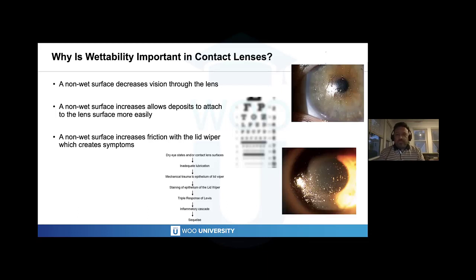This is crystal clear. If you ever have a patient who develops some type of lid palsy, lid paresis, whatever, where they're not fully blinking, you're going to see the lens forming deposits over the surface of the lens where the lids don't close and where they don't re-wet that lens with each blink. So a drying of the lens surface allows deposits to attach. And so by keeping the surface wet as much as possible, we actually reduce depositing on that lens surface as well. And then a non-wet surface also increases friction with the lid wiper when we blink.